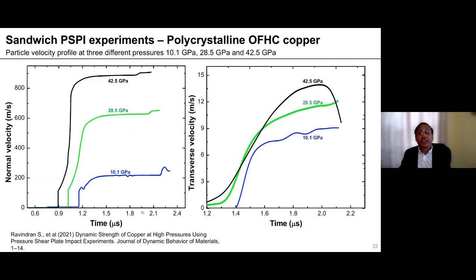So now let me start showing you the results on the copper. I plot the normal velocity and the transverse velocity. The normal velocity is plotted here. Once again, you can see the Hugoniot elastic limit. As I mentioned, the normal response is dominated by the tungsten carbide, which is to be expected, which is just the pressure wave response.